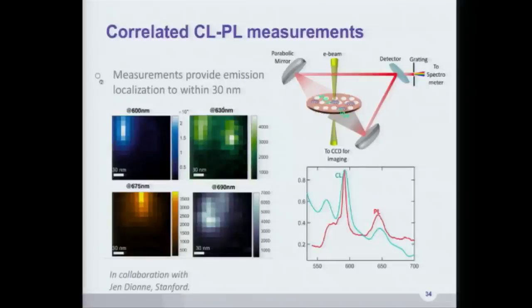So what they do is they measure PL from a specific set of emitters. Then they measure the cathodoluminescence, and something they surprisingly find is that they go back to that same spot, and they find PL again. What that tells us is that whatever the beam is doing, it is not destroying the emitter, which is very surprising, because most often when you look at hBN under an e-beam, it should just disappear, or something bad should happen to it. So we suspect, and this adds some more credence to the idea, that the emitter could be this very non-equilibrium configuration that's hard to form, but once formed stays there because it's, say, near grain boundaries and other kinds of defects, and maybe it's somehow stuck.